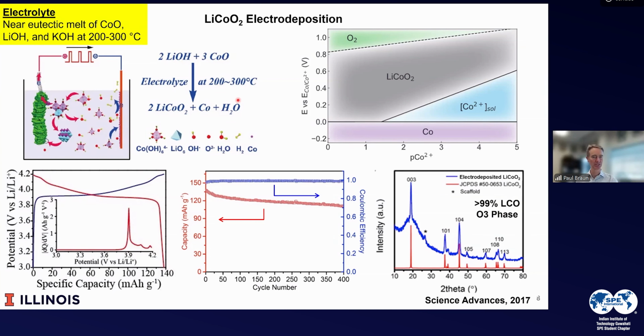And the material that's formed is very high quality. So if we look at the specific capacity, it's near theoretical. One sees all the features you would expect to see in highly crystalline lithium cobalt oxide. When we build it into a cell, it cycles quite efficiently. So this cycles 400 times with a Coulombic efficiency of near unity. And the material as grown is nearly phase pure. So indeed, what we have is a high quality cathode material containing no binder and no conductive additive. And as I'll show in some of the subsequent slides, it's very highly oriented in a way that enhances the energy and power density.